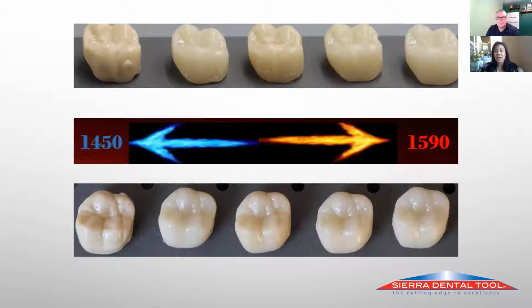And then lastly, I did one at 1590, which is 40 degrees Celsius higher than the recommended temp. And you can see that all of the chroma has been burnt out. It's very low in value, and it's also going to be more translucent. And when we've gone really far over the IFU, we are also compromising the strength of the zirconia. So we want to be very careful that we are following the IFU. You are safe to go 10 to 20 degrees higher if need be, but if you find yourself doing that, that's probably because your furnace isn't calibrated.